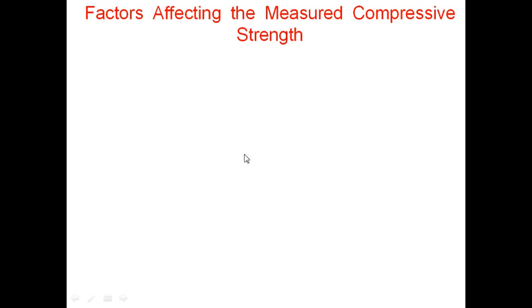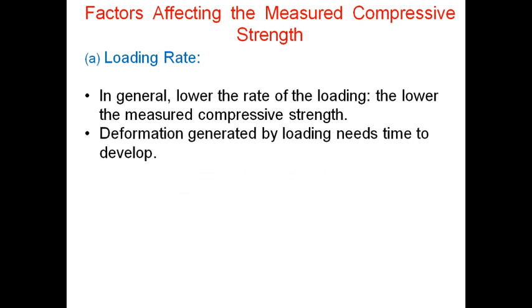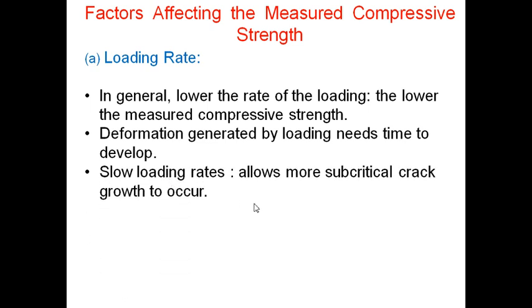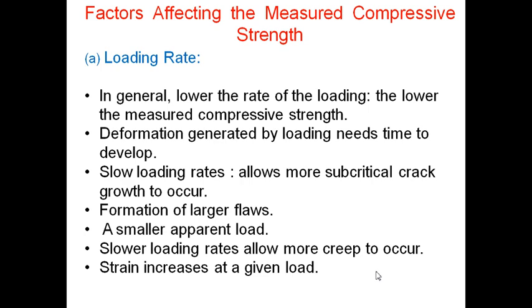Now let us see factors affecting the measured compressive strength of concrete. First, very important is loading rate. In general, lower the rate of loading, the lower the measured compressive strength. Deformation generated by loading needs time to develop. If we keep the loading rate as slow, it allows more subcritical crack growth to occur, and therefore there will be formation of larger flaws, and we get a smaller apparent load and low strength. Lower loading rates allow more creep to occur in the concrete, strain increases at a given load, and therefore limiting strain is reached, which indicates the failure of the concrete.